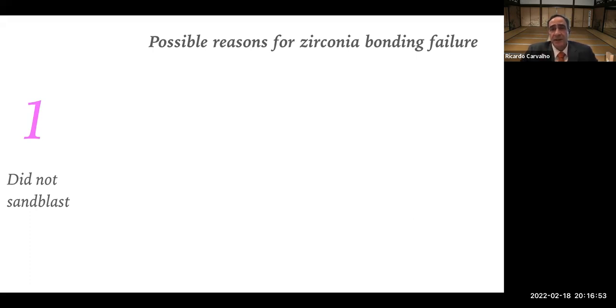And when we look at the clinical data or literature, clinical studies, we will easily see that one of the most technical problems with zirconia in clinical evaluations is exactly the debonding of zirconia. You will rarely see zirconia breaking. You will see veneers chipping, veneers breaking, but the zirconia itself, unless there's a big mistake in the designing, will rarely break. But the failures that we see clinically are usually associated with debonding.